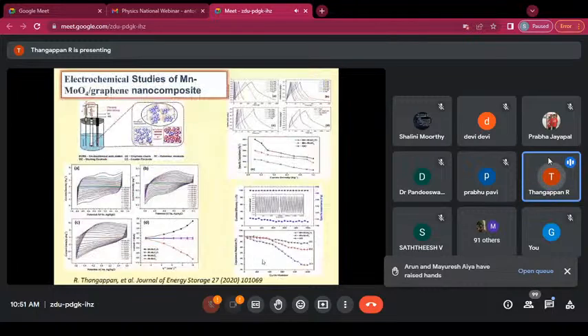Electrochemical studies were performed on the composite material, and here also we studied the three-electrode system. We achieved above 300 farad per gram at 1 ampere per gram current density, and the stability of the material is very high, 97% for the composite material, while for the pure material the stability is very low. With that, we concluded that the material can be used as an electrode for supercapacitor applications.